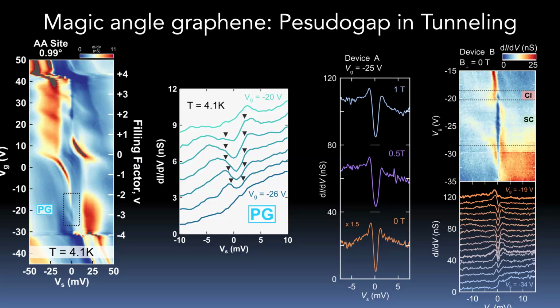Experimentally, if you move the tip to another equivalent site, is the data reproducible? Yes, it's highly reproducible, and actually compared to cuprates, this is a highly homogeneous gap. There is no doping inhomogeneity in the system to speak of. There is twist angle inhomogeneity, which is there, but we can kind of correlate that and stay away from those regions.